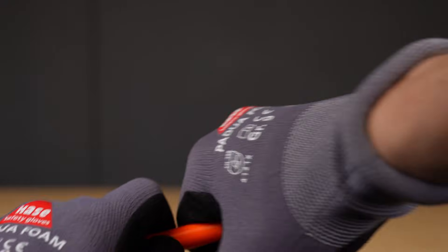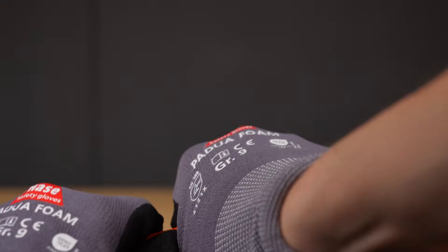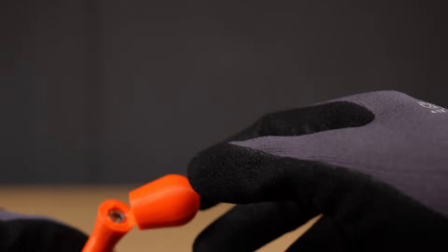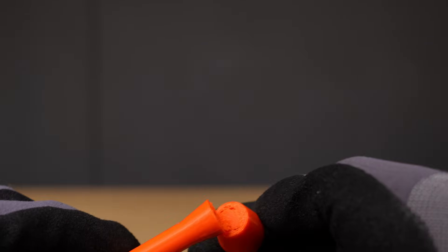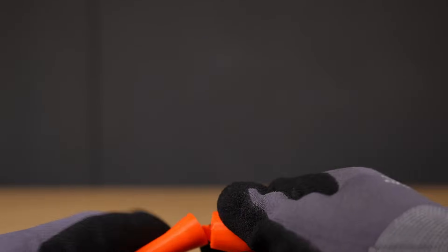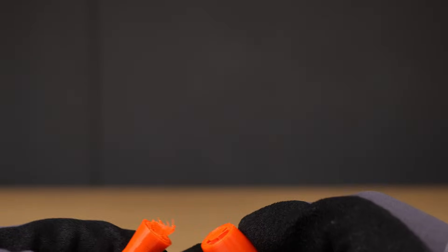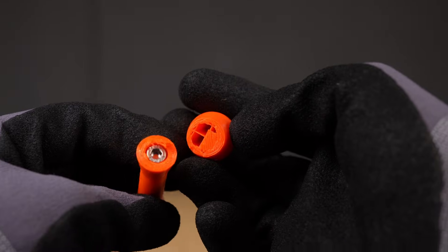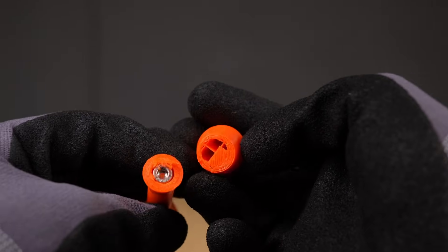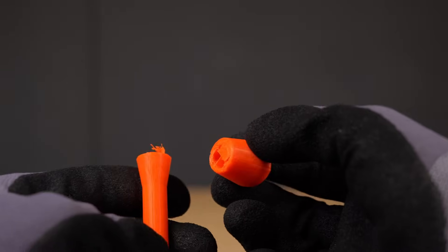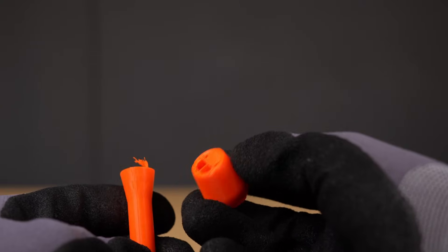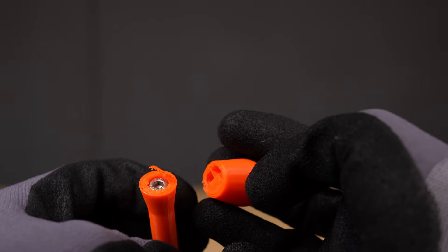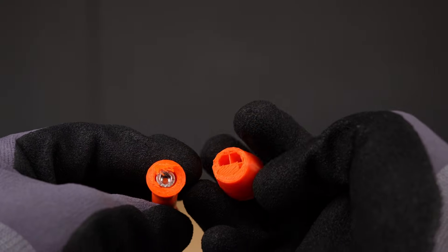I had to apply a lot more force and when it finally did break, it didn't fail in the middle where I added the screw. It broke out in a completely different area above the screw where there was no reinforcement. That's a good sign. It means that the reinforcement zone was no longer the weak point and it works exactly as intended.